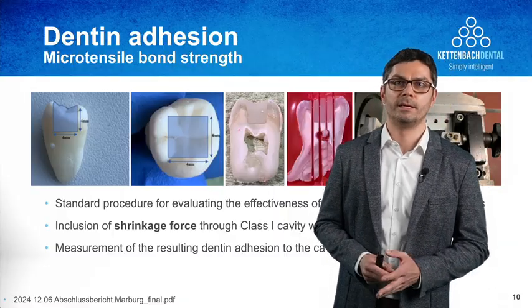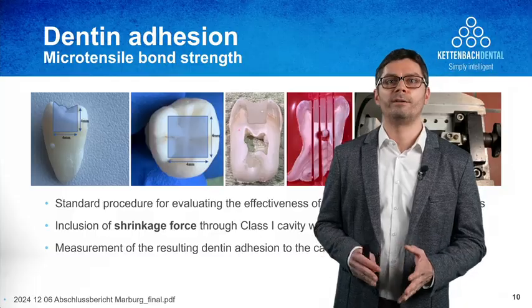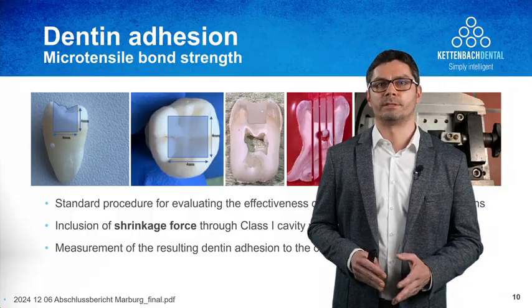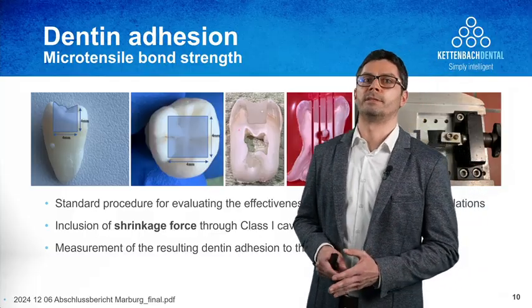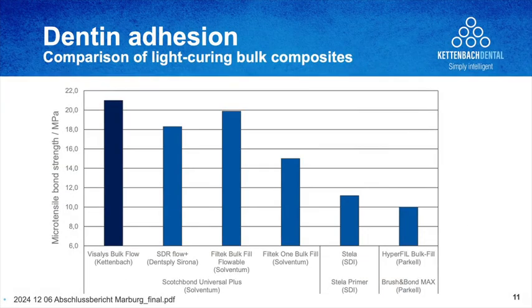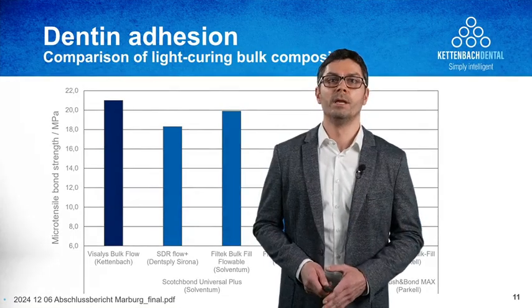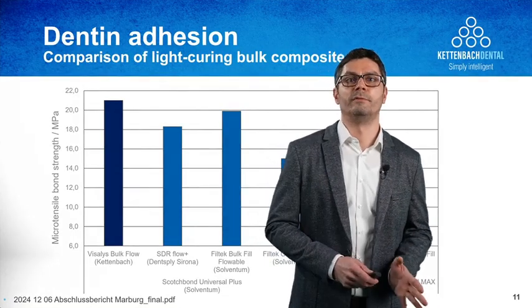And as you can see here, this very big cavity has a very high C factor, and therefore is really the worst case for restoration material. So if you now have a look at the results of the dentin adhesion, you can see that this very low shrinkage force indeed leads to a high dentin adhesion, as you can see here on the left for Visalys bulk flow. So the theory is approved, so to say.